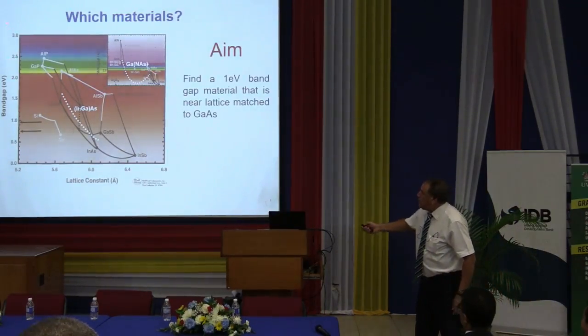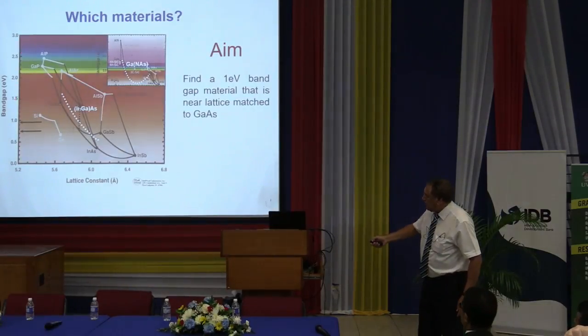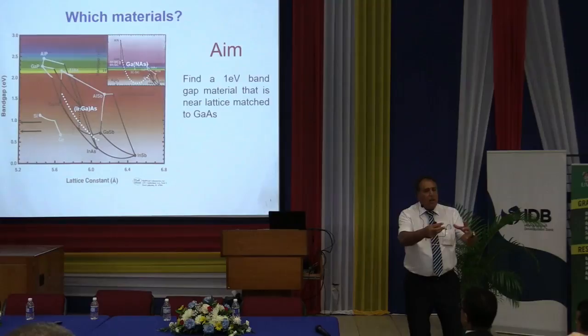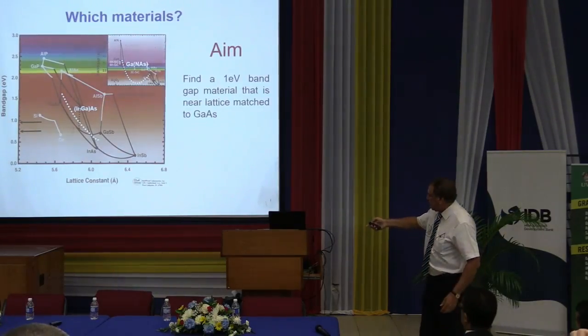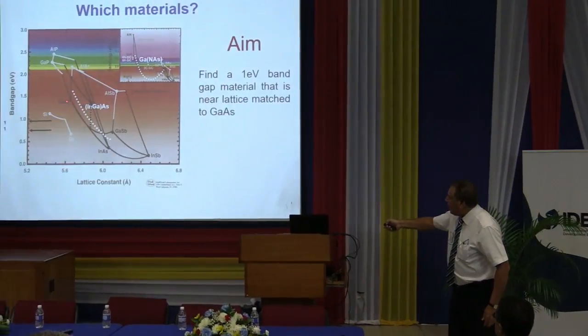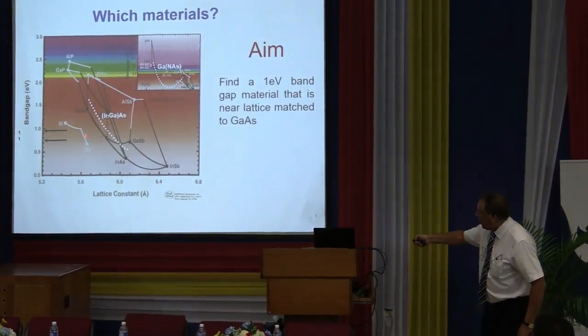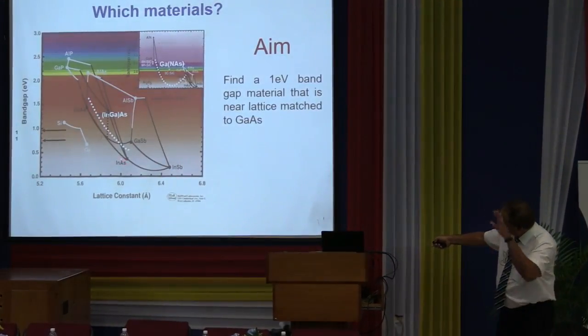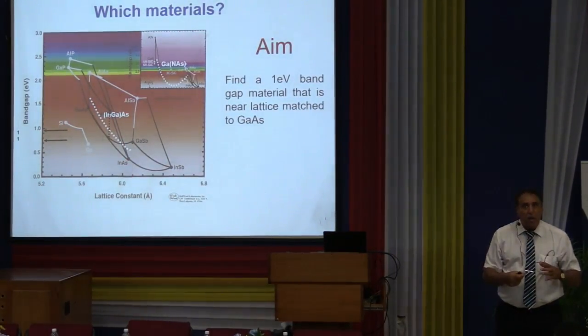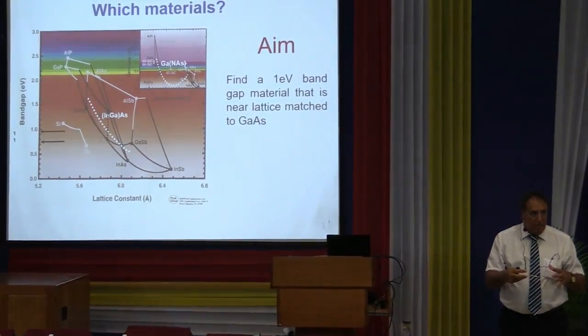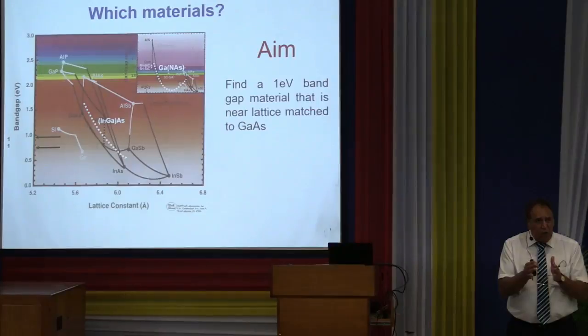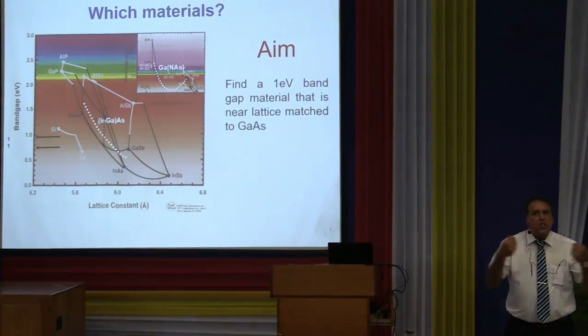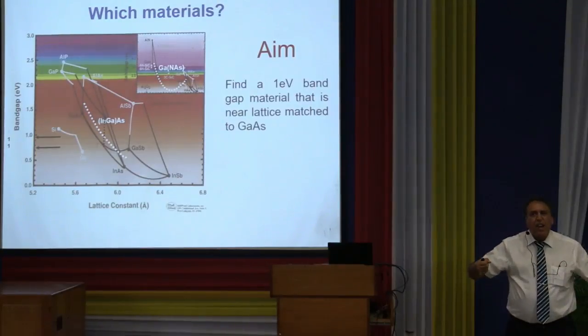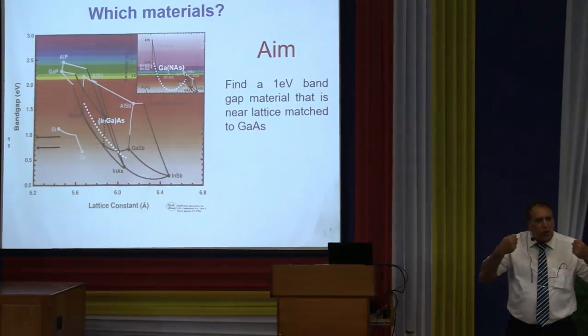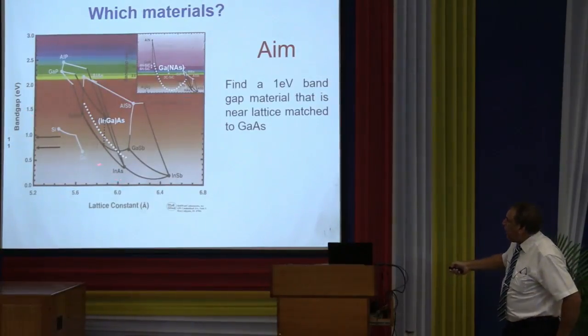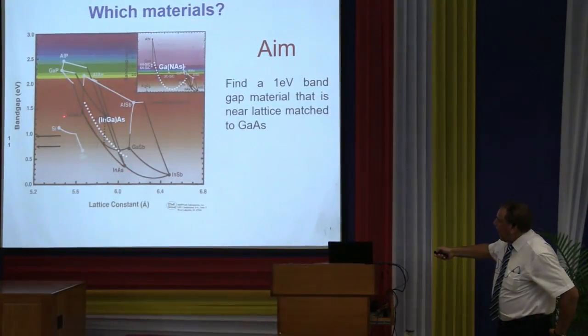So look here. This is the energy of semiconductors as a function of the size of the crystal, that's how big the crystal is. Take, for example, gallium arsenide: the size of this crystal is about 5.6 angstrom. If you take indium arsenide, another group 3 compound, the size of the crystal is 6 angstrom. Remember, an angstrom is 10 to the minus 10 meters. It's a very small difference in the size of the crystal, but it makes a huge difference in terms of strain, because they have different sizes, and if you put them on top of each other, they create a lot of strain.